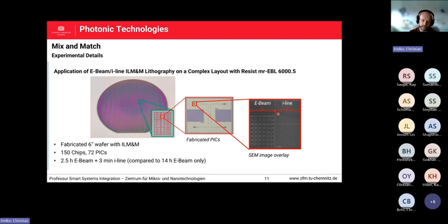For the time aspect, for example, exposing the whole wafer with E-beam, the whole system took 14 hours, despite the fact that the photoresist is really fast. But if we use the mix and match approach, we just needed 3 minutes for I-line. In reality it's just 1 minute, but with handling it's 3 minutes per wafer, and 2.5 hours in the e-beam tool itself. So it's quite fast. A lot of wafers can be exposed in a shorter time, and can be used by our etching colleagues to destroy all of the wafers. Hopefully not.